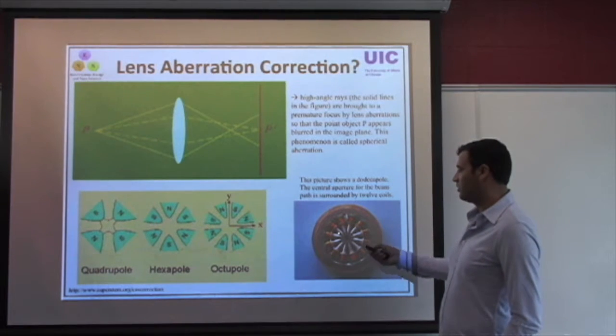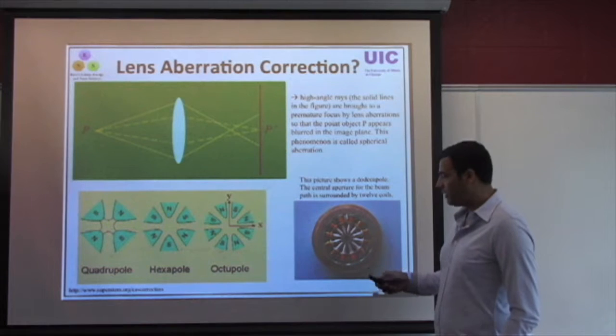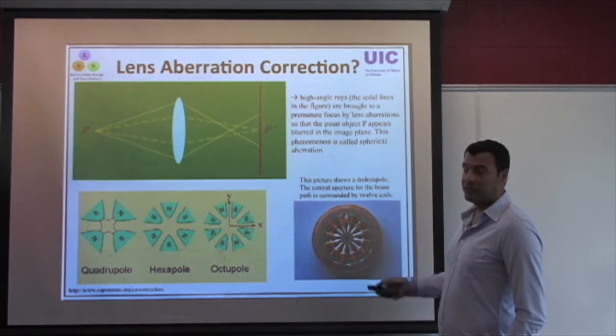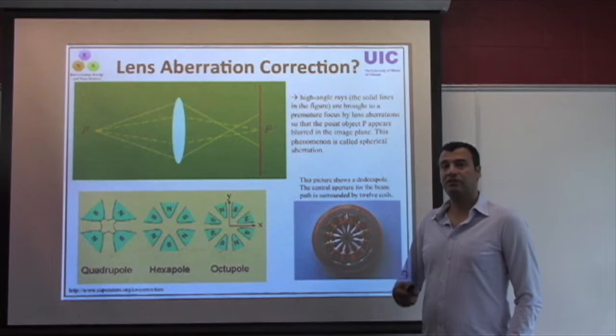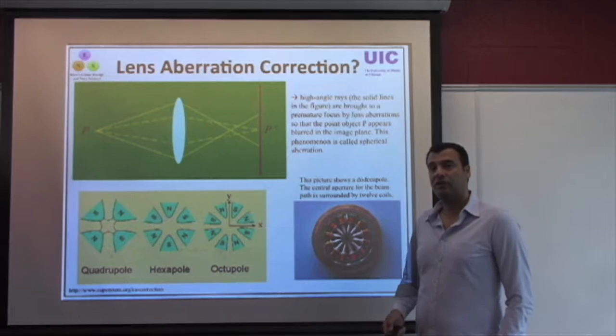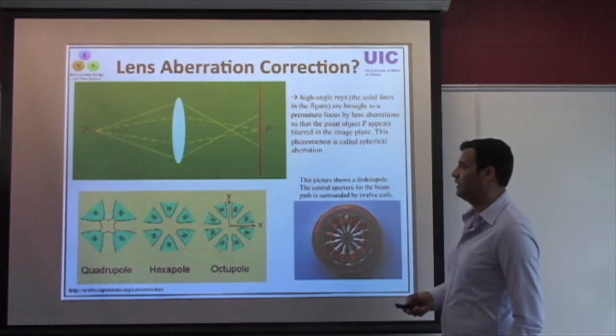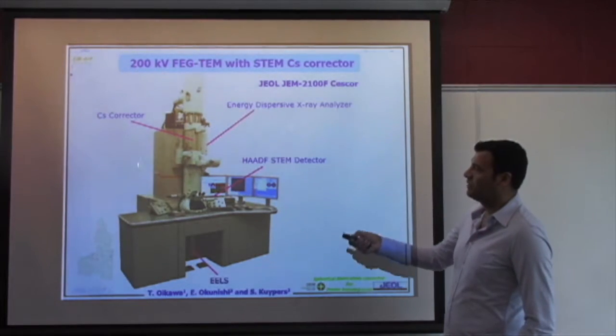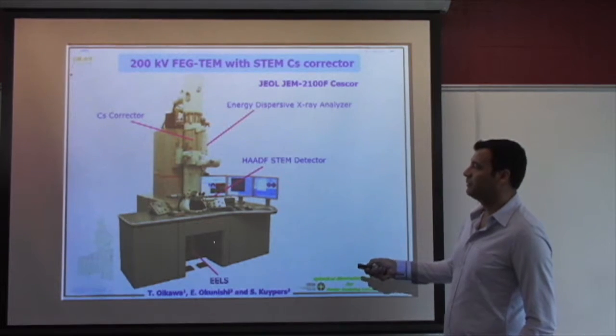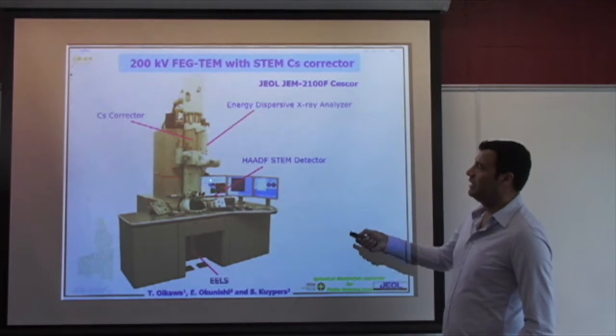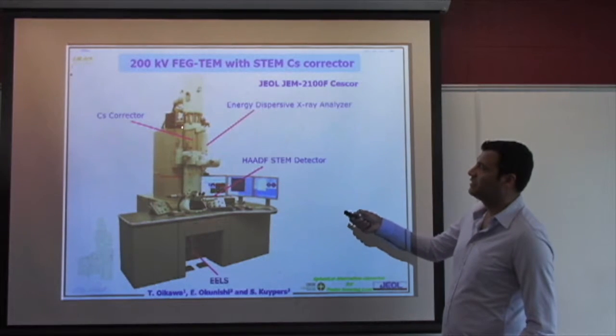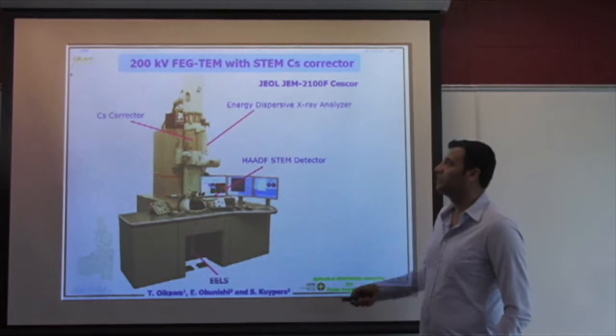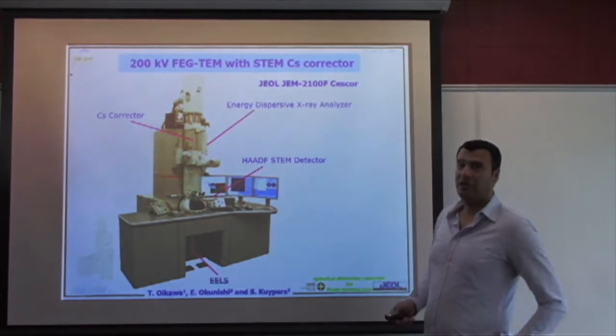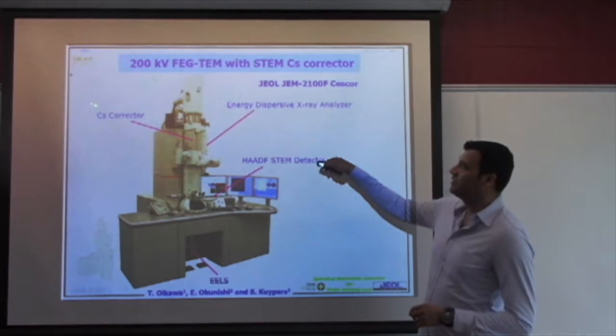And this is an example of one of these corrected systems. If you add this corrector to your electron microscope, then you can get far better image resolution, and also far better chemical resolution in your analysis. This is an example of one of the electron microscopes. This is where you input your sample, and the CS correctors, which are spherical aberration correctors, these lenses are placed above the sample. And this is the electron beam gun.